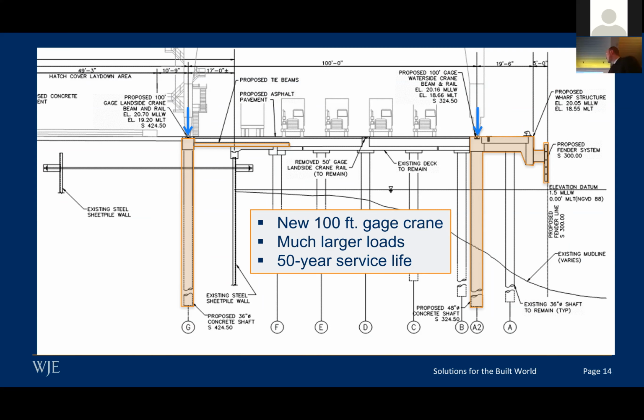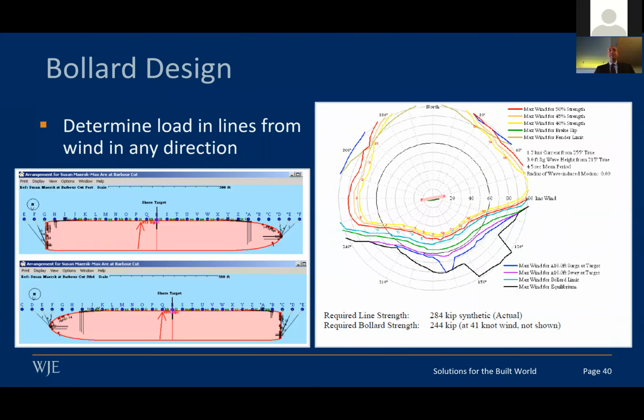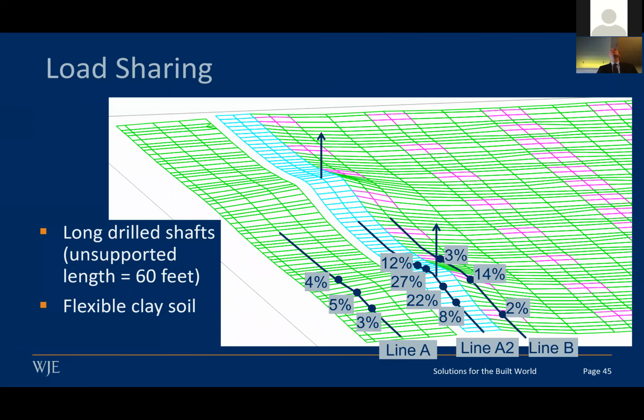So along the land side, the left side of this plot, everything is going into the new structure. And there's no water there, so they're not extending 60 feet unsupported. And so those drilled shafts in general are going to be much stiffer. Whereas on the water side, the crane beam is actually getting shared between multiple elements. And that's where I was showing some slides later on that showed that sharing effect.